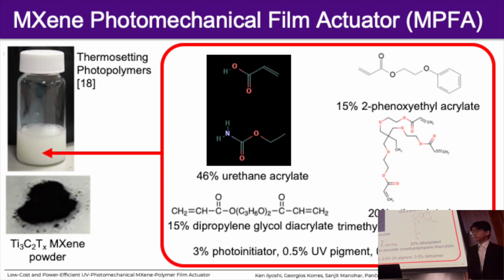Right, so instead of liquid crystal elastomers, which we weren't able to make in, let's say, 1 month before the deadline, we had a thermosetting photopolymer to use instead for the purpose of this conference. So what this thermosetting photopolymer is composed of are just some polymers. Mainly urethane acrylate, which gives the rigidity and the toughness. This is used in normal SLA printing, so resin printing in general. And some copolymers, mainly to accelerate the photopolymerization process, or to make the resin a little bit more liquidy, aside from a little bit of photoinitiator, UV pigment, and defoamer, of course.